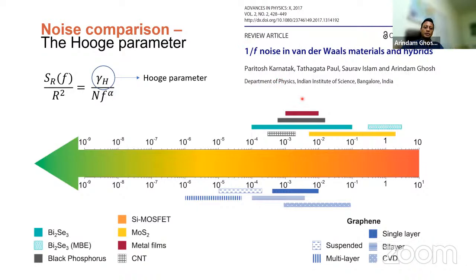you can see the Hooge parameter is maximum here and minimum here. These are different two-dimensional systems. If you take a silicon MOSFET, you have usually a very large noise. But these lower bars are from graphene. Okay. Silicon, when we started originally, the single layer graphene, the noise level was about a Hooge parameter of about 10 to the power of minus 2, 10 to the power of minus 1 region.